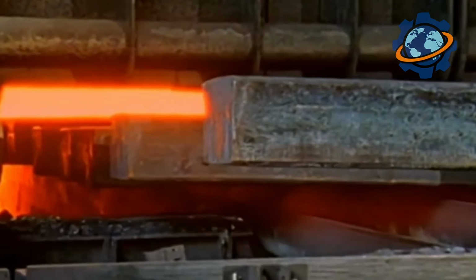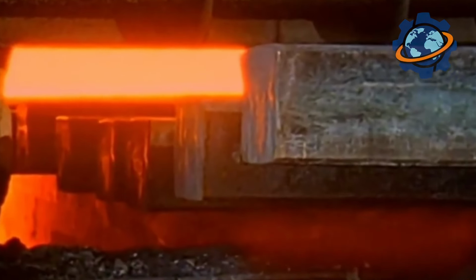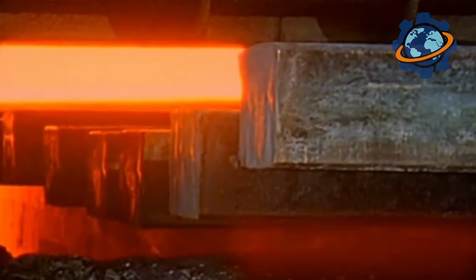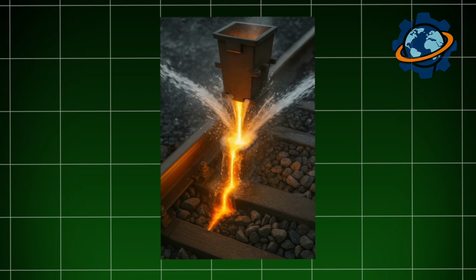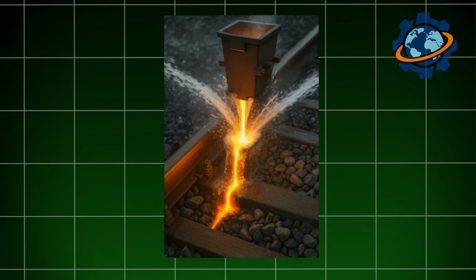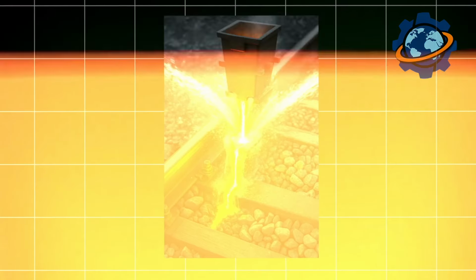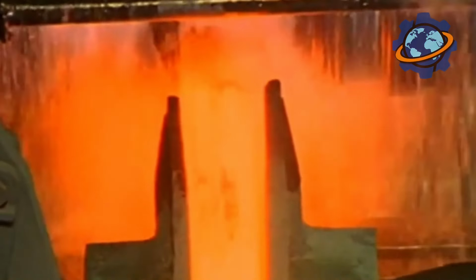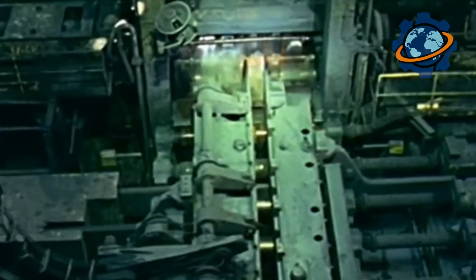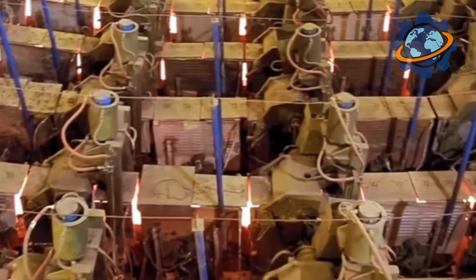The rail is instantly cooled. Jets of high-pressure water are aimed along the head and web, the very parts the wheel rolls on. The temperature drops in a flash, and a new structure forms in the metal, martensite, an extremely hard, wear-resistant phase. But to avoid brittleness, the rail is slowly heated and cooled one more time.